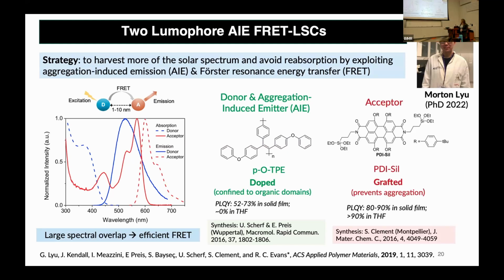Our acceptor is going to be this perylene diimide dye. And you can see that it's modified at the ends here with these orthoethyl silicate groups. And if we do the acid condensation, the sol-gel reaction with our lumiphore in place, this lumiphore grafts to the silica domains. And this prevents aggregation, which can be an alternative loss mechanism in these systems.